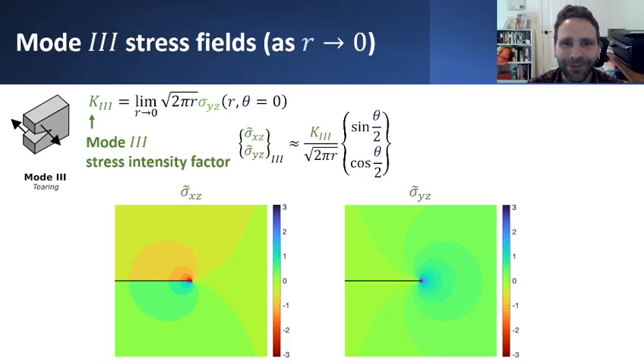So there's no way to really formulate a stress-based failure criterion, at least one that applies to these approximate solutions that admit infinite stresses, because how do you formulate a criterion that involves an infinite stress? At least any such criterion we could develop that would be purely stress-based would tell us that, regardless of what that criterion says, the crack should have already happened. The stress is going to be infinite regardless of how much load we're applying. So how do we know when fracture will actually start?